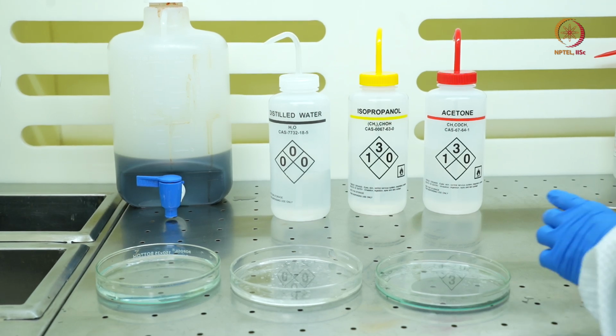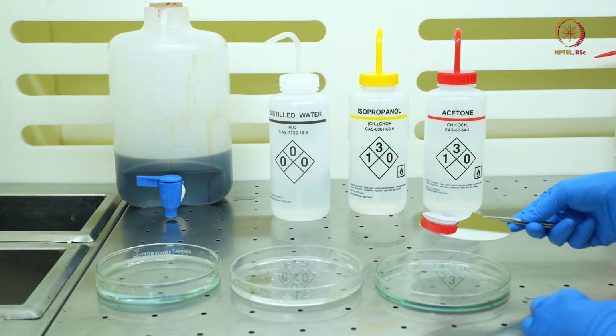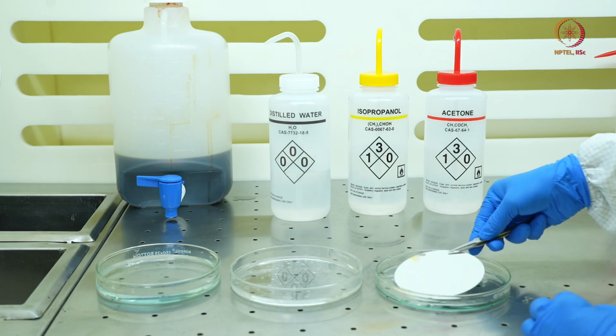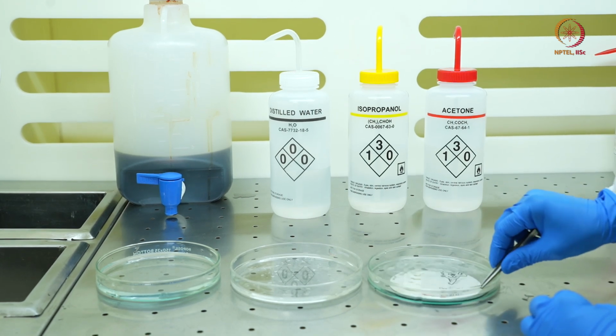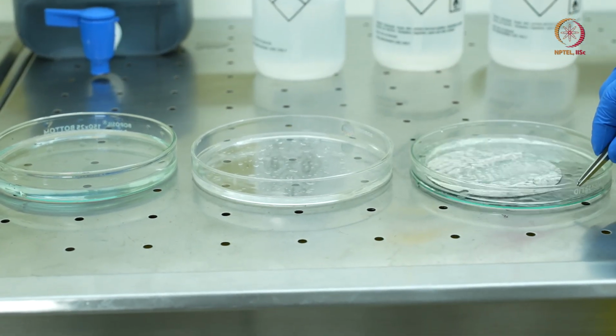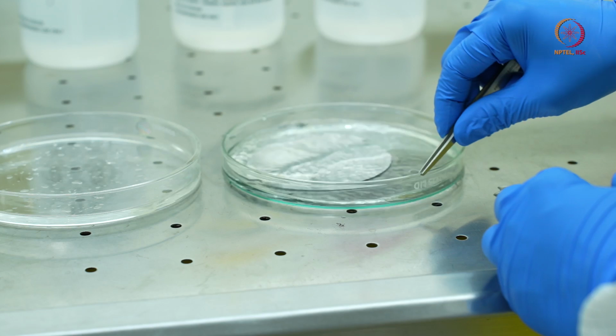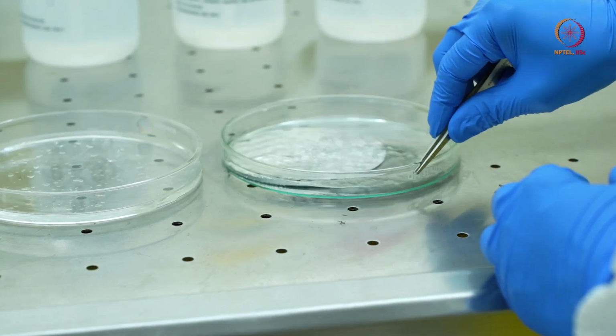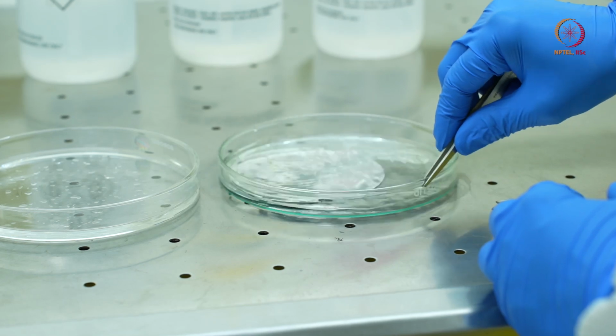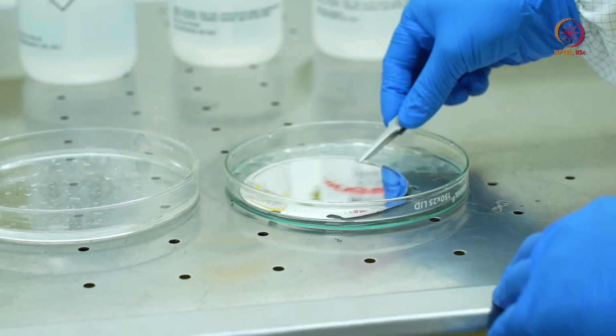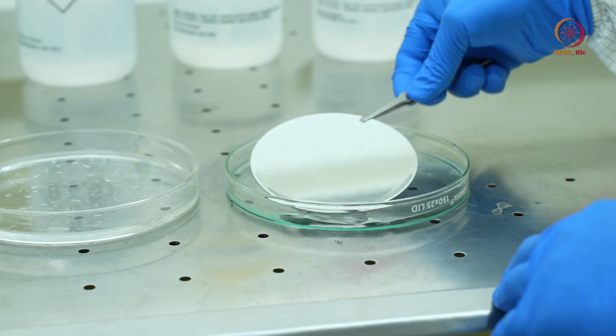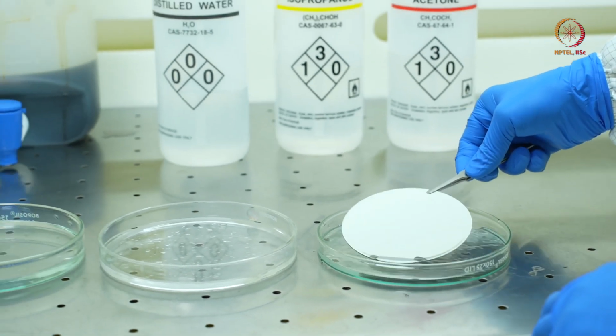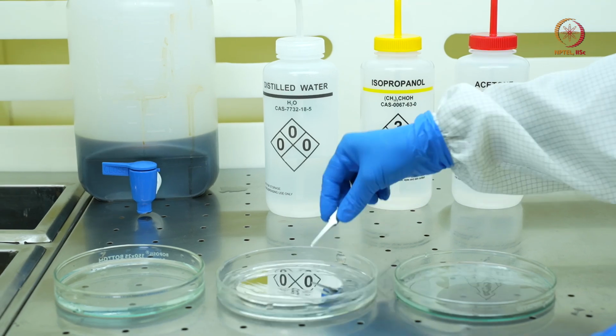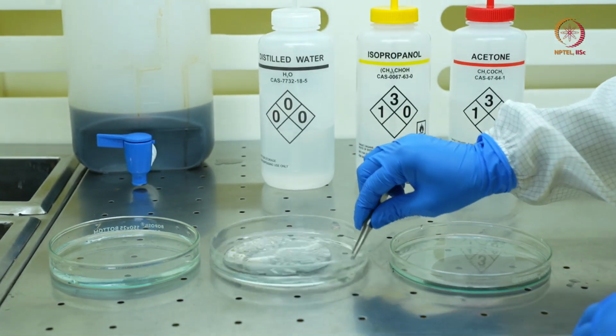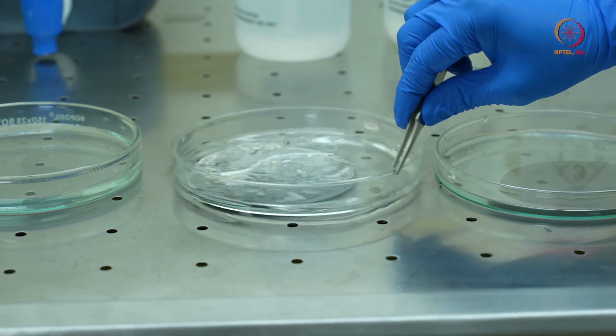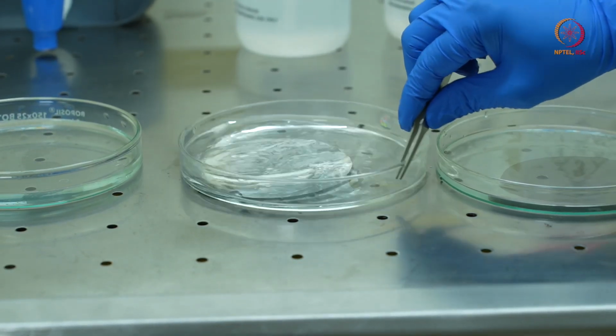Now I'll take my sample using this tweezer, and with the support of my hand, I'll dip it in acetone. Once it is completely dipped, I'll start agitating it so that the cleaning is proper. I'll continue this for about 2 minutes, and then we will move to IPA. We have agitated it for 2 minutes. Now we will move the sample from acetone to IPA, the isopropyl alcohol or isopropanol. Again, we will continue this agitation in IPA for 2 minutes, and then we'll move to DI water.